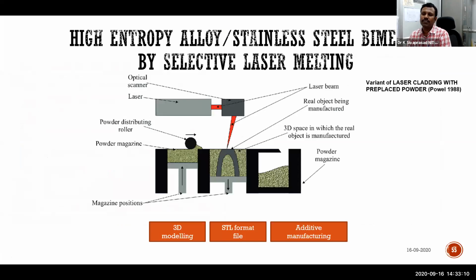Next, welding was done. Welding proved that around 80% efficiency was observed. But we want to do the same thing through selective laser melting, additive manufacturing. In this also, we don't want to do only high entropy alloy separately and nickel-based superalloy separately and then weld them. No. The layer itself we want to build as a bimetal. First, say Inconel, I will build a particular thickness, then I will stop, drain the powder, and fill with high entropy alloy powder, then start melting with another thickness. Say 4 mm: 2 mm for high entropy alloy, 2 mm for Inconel, or 2 mm for high entropy alloy, 2 mm for stainless steel. Like that, I started building. That is a novelty associated with the additive manufacturing concept we have considered.